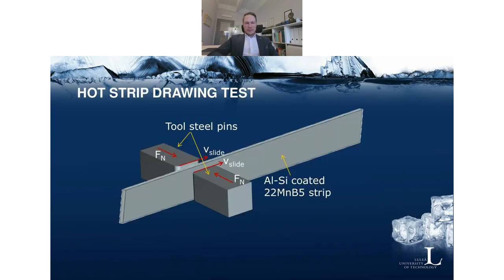This is the test configuration. So basically it consists of a strip. This is an aluminum silicon coated boron steel, where the aluminum silicon coating is the problem. That's the one that transfers to the tools. This is pinched between 2 tool steel pins that we load against the strip, and then they slide in the horizontal direction along the strip for 200 millimeters in this case. The tools are not heated in this case, only the strip is heated.